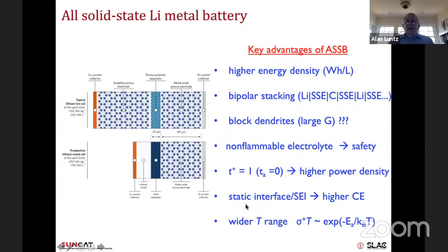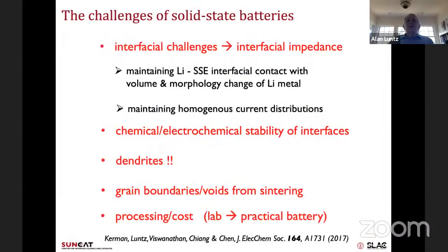In principle, you have a static interface between the metal and the electrolyte. This means you don't keep reforming this SEI all the time. Part of it reforms in a liquid, but here you don't reform it and it's static. So in principle, that should give you a higher Coulombic efficiency. And it turns out you actually can get a higher temperature range in principle. But of course, nothing is for free. There are all kinds of challenges with solid state batteries, which many people are working on now.